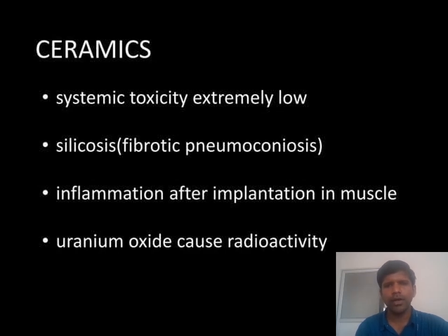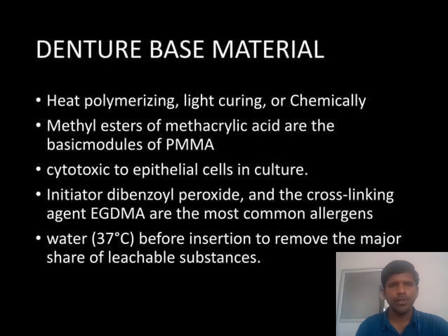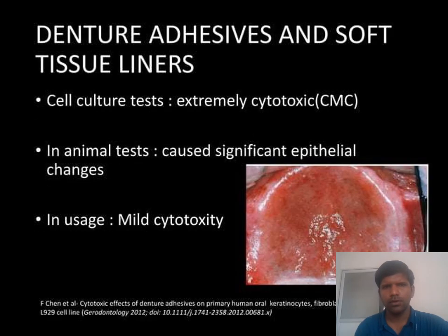Uranium oxide causes radioactivity. Coming to the denture base material, it may be heat polymerizing, light curing, or chemically curing. Methyl esters of methacrylic acid are the basic modules of polymethyl methacrylate. It is cytotoxic to epithelial cells in culture. The initiator, dibenzoyl peroxide, and the cross-linking agent, ethylene glycol dimethacrylate, are the most common allergens. Soaking in water at 37 degrees Celsius before insertion is done to remove the major share of the leachable substances.